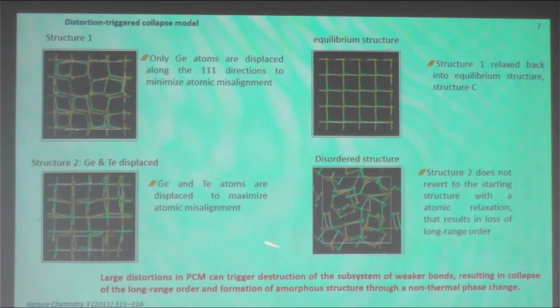By this, this mechanism can also be considered a non-thermal phase change, and it suggests that, if you somehow can make it possible by experiments, then you can transform from the ordered to the disordered structure simply by distorting the germanium and tellurium atoms, both of them.